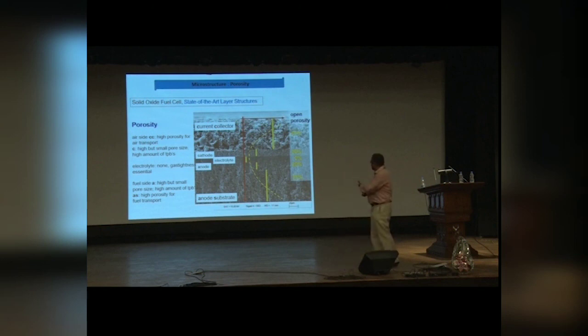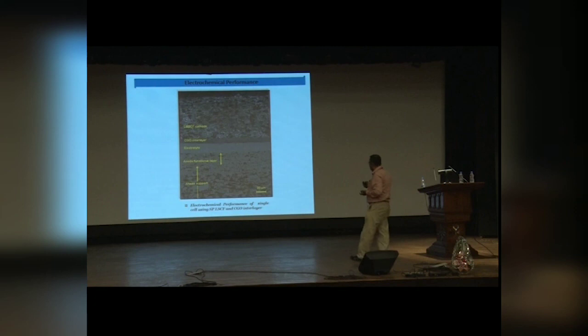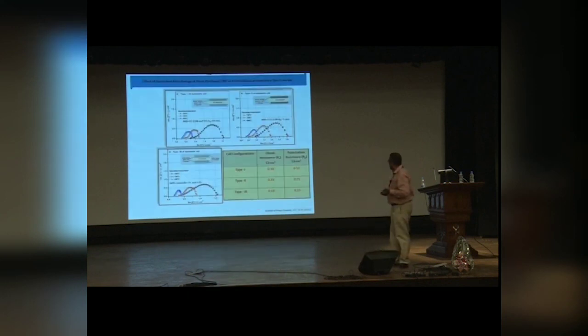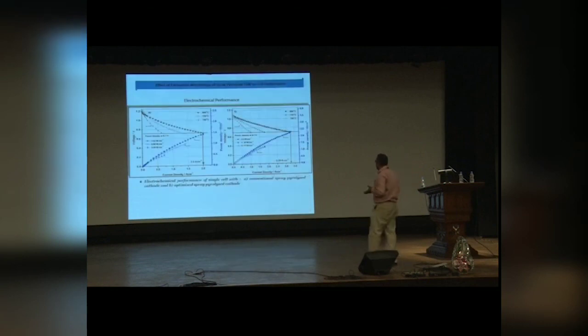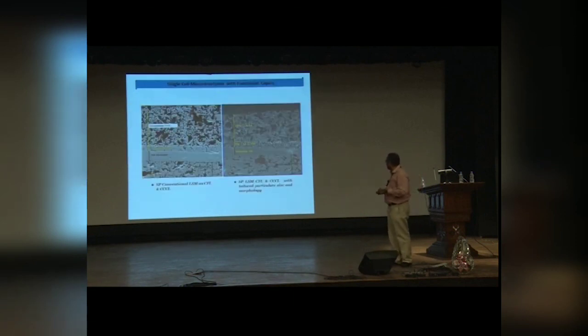So that result I will show you. These are some of the analyses which we have done. I am not going into that, but this is the microstructure which we produce, and there you can see that different kinds of materials have started coming. That is basically gadolinium doped ceria and lanthanum, cobalt, iron and strontium based materials. There we did a lot of impedance spectroscopy to find out which type of material is suitable, and with that idea we have gone to what I showed you earlier. There we have increased our current density much more by optimizing the spray pyrolyzed cathode materials, and these are all